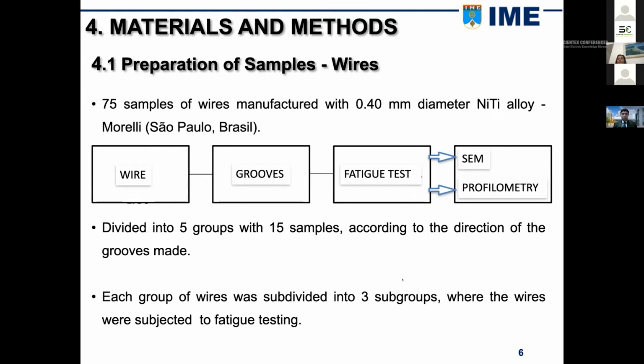Each group had 15 samples that were divided into 3 subgroups for the rotation flexion test. The first subgroup was tested until it fractured. The second subgroup was tested at 50% of the mean fatigue time of the first subgroup. And the third subgroup was tested at 75% of the mean fatigue time of the first subgroup. The wires were tested in the rotary bending test. After the test, the samples were analyzed in the scanning electron microscope and the optical profilometer.